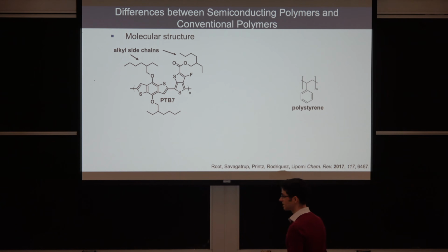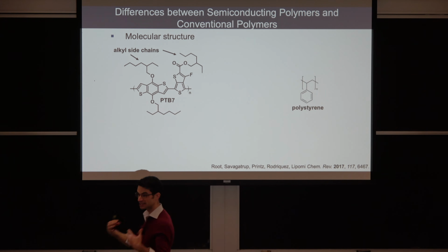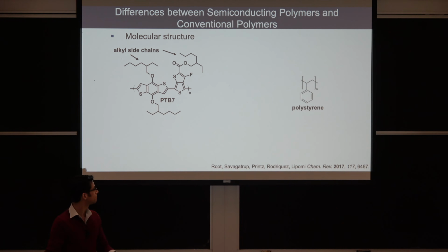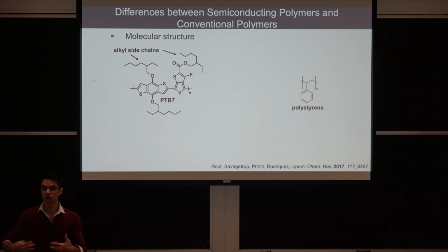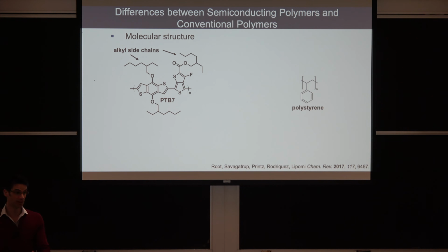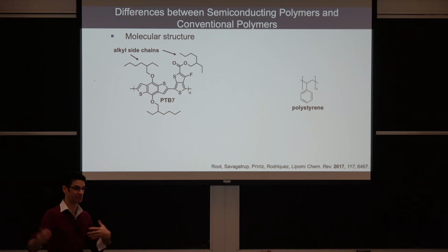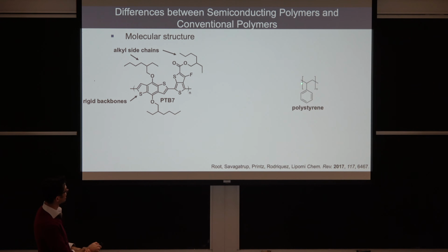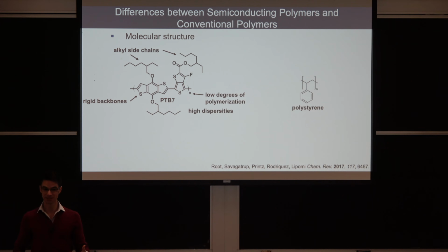So what do we have? We have these alkyl side chains. The alkyl side chains serve to solubilize the material. How do they do that? Because this chain is rigid and these chains are floppy, there's an entropic benefit in solubilizing a material that has these side chains on it, because they can occupy lots of different conformational space. So we have these rigid backbones, whereas the backbone here is flexible. We have low degrees of polymerization, and this is a result of the synthetic procedure that you need to make these materials. Also, the higher your degree of polymerization, the less soluble these materials tend to get.